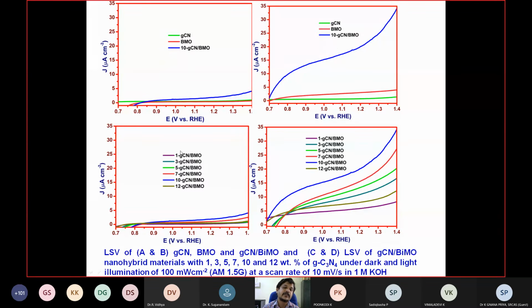Here also we have varied the different weight percentages of graphitic carbon nitride. There is no appreciable change in the dark condition. Once we switch on the light, you can see there is an enhancement. This is how we optimized. Then we found that the 10 weight percent graphitic carbon nitride bismuth molybdate heterojunction showed the superior activity.